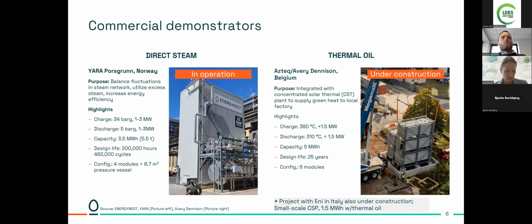Some more details on our commercial demonstrators. On the left side, again, this is the plant we have in operation with Yara in Norway. This is a direct steam solution connected to their steam network. And here we are balancing fluctuations in the network at 34 bar with excess steam, and then discharging to the low pressure steam network. This improves energy efficiency and reduces fluctuations in the steam network.